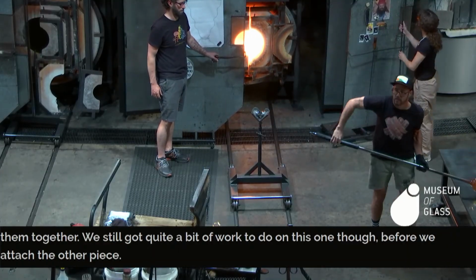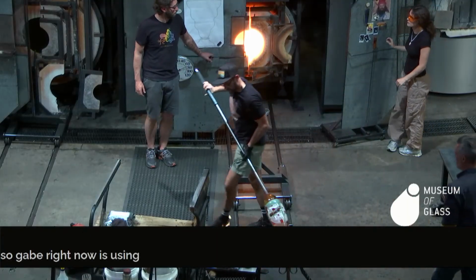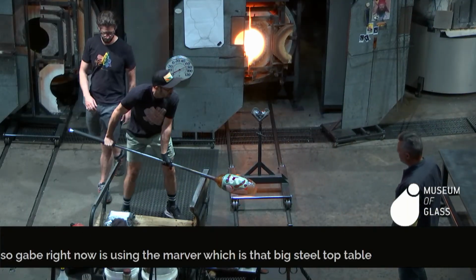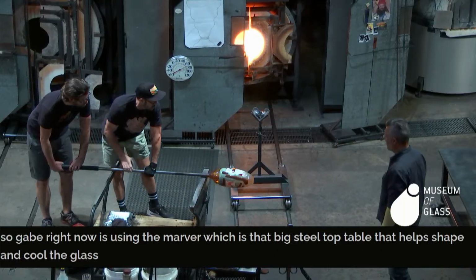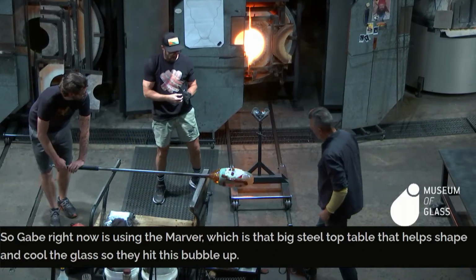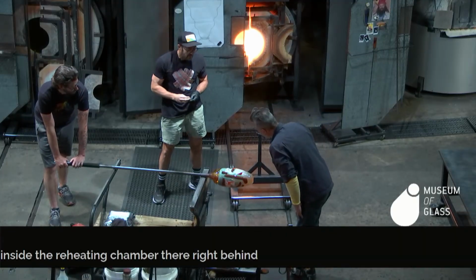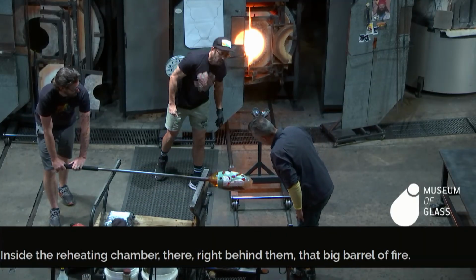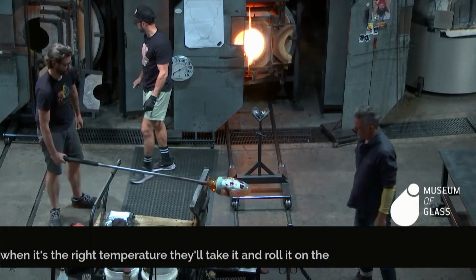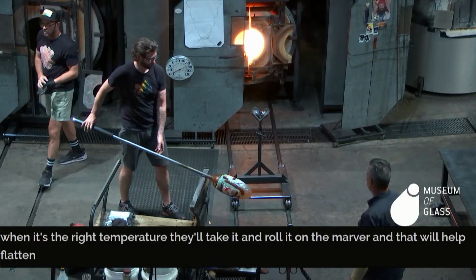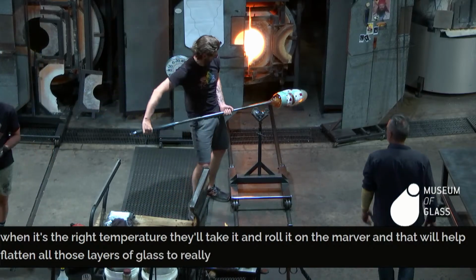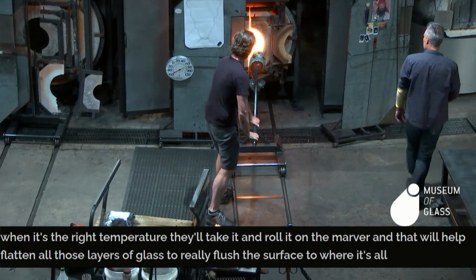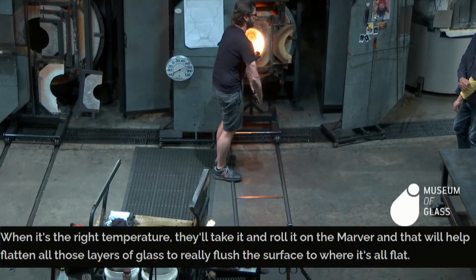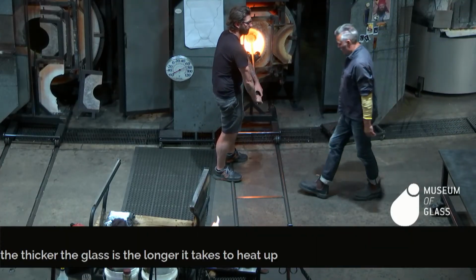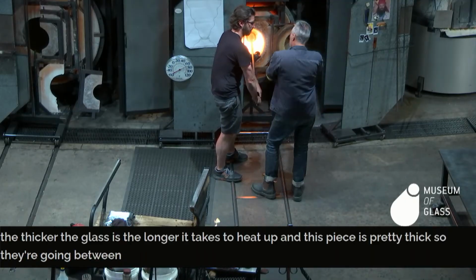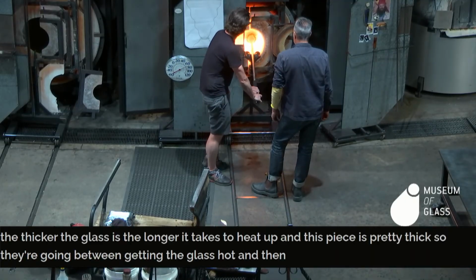So Gabe right now is using the marver, which is that big steel top table that helps shape and cool the glass. So they heat this bubble up inside the reheating chamber there, right behind them, that big barrel of fire. When it's the right temperature, they'll take it and roll it on the marver, and that will help flatten all those layers of glass to really flush the surface to where it's all flat. The thicker the glass is, the longer it takes to heat up, and this piece is pretty thick.